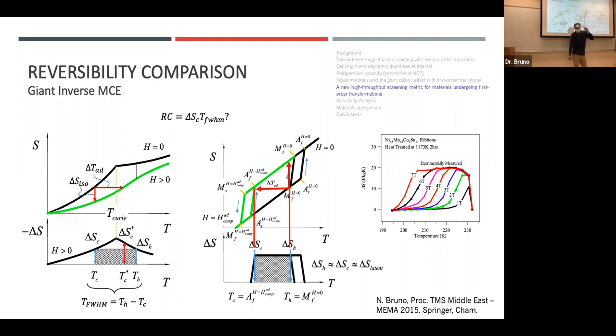And in experimental data, you don't have those critical temperatures labeled. You don't have a feature to find what that is. A lot of the time in the literature, when researchers describe the refrigeration capacity of these materials, they just integrate these curves without any regard to reversibility. So obviously you're going to have huge refrigeration capacity for these things in comparison to non-shape memory alloys because you have a huge entropy change curve. The entropy change is simply the difference in entropy between austenite and martensite phases through the latent heat.